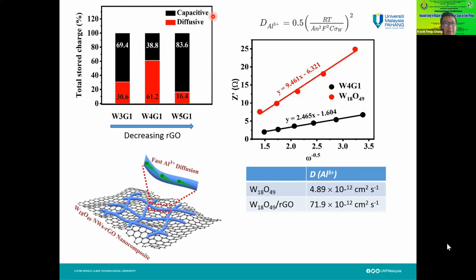And then this diagram actually tells us what ratio should be used. We use the ratio of 4 parts tungsten oxide to 1 part graphene. It can have a very high diffusive behavior.